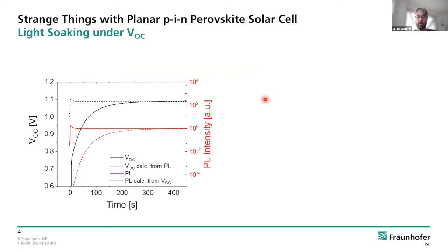When we measured those solar cells, after they had been in the glove box for 2 or 3 days, we saw something that was very surprising for us. Here you can see on a time scale of several hundred seconds the open circuit voltage. This is the black line. And at the same time, we measured the photoluminescence intensity. This is the red line. And this is something which you would not expect like this, because in a solar cell, usually the open circuit voltage and the photoluminescence intensity are somehow very strongly linked to each other.